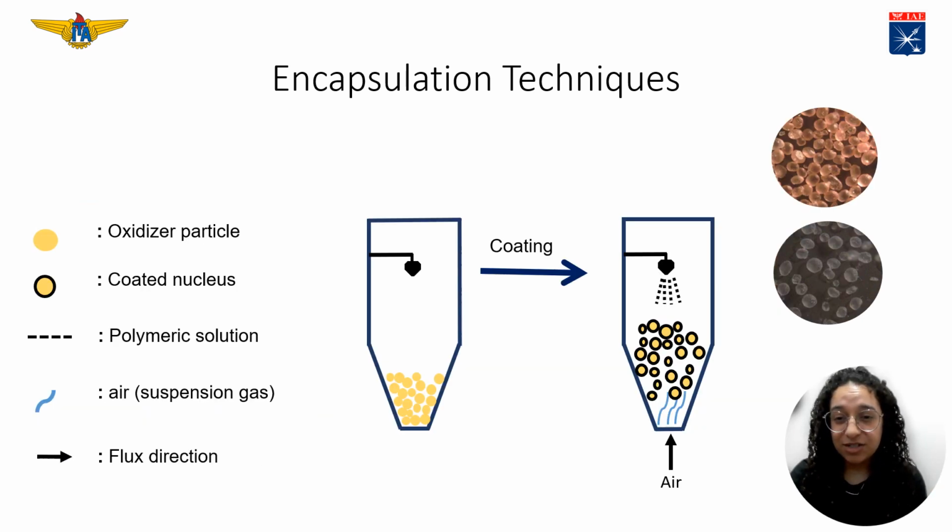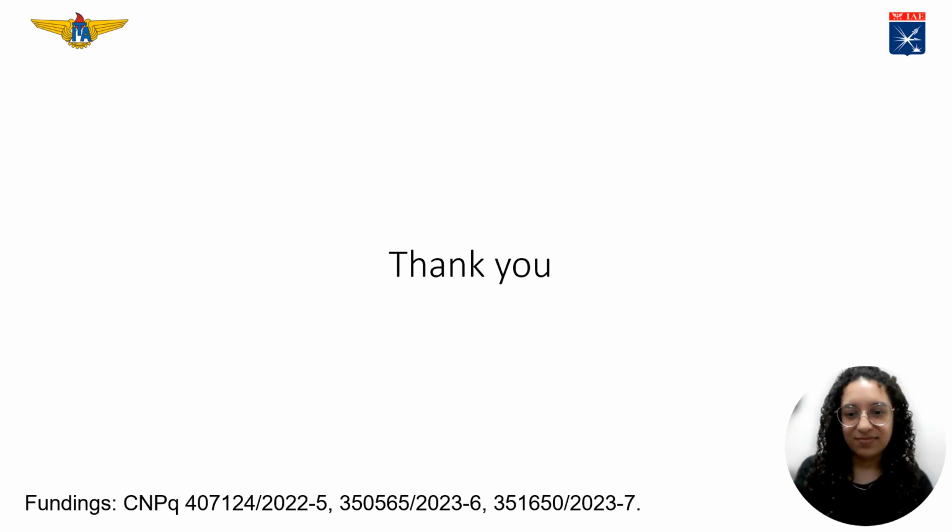The last encapsulation technique is the fluidized bed, where the particles are suspended, rotating inside the chamber, and a coating solution is sprayed on top of the particles. The solidification happens by the evaporation of the solvent. These techniques are valuable tools to promote shape modification, diameter control, or to adjust a specific property of energetic particles applied to propellant formulations. Thank you.